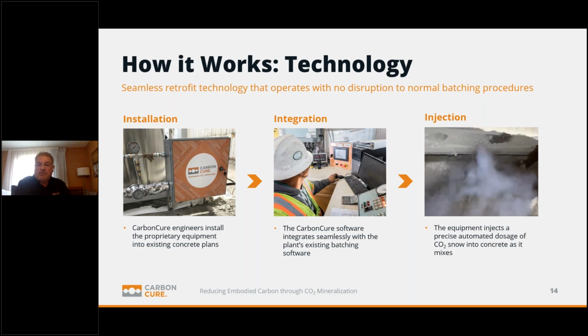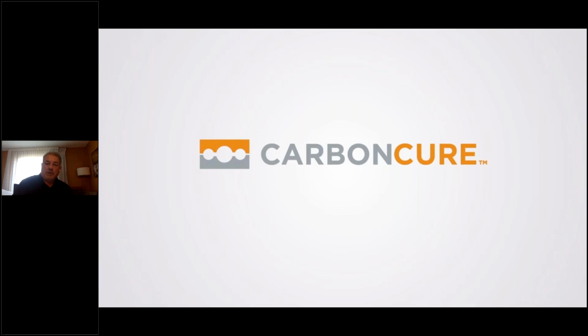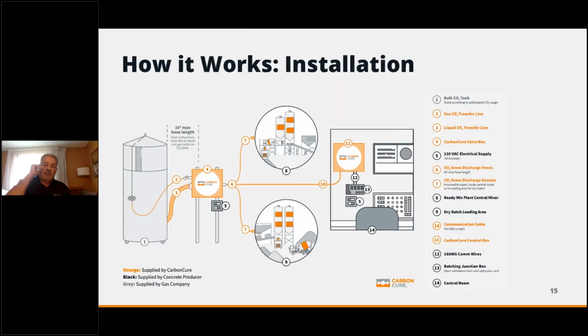And then the final phase, once all of that equipment is bolted on, we actually control the equipment to deliver a controlled amount of CO2 into the concrete as it mixes. So although that doesn't look overly precise there, think about what happens when you have a fire extinguisher and you're spraying something. CO2 kind of looks like that when it goes in. So there's an injection nozzle that's placed. If it's a central batch system, it's actually placed and dispensed where all of the raw materials will go in. On a dry batch system, we're basically dispensing the CO2 on top of that. But regardless, we work with the engineering teams at the concrete producer to optimize that mix design.